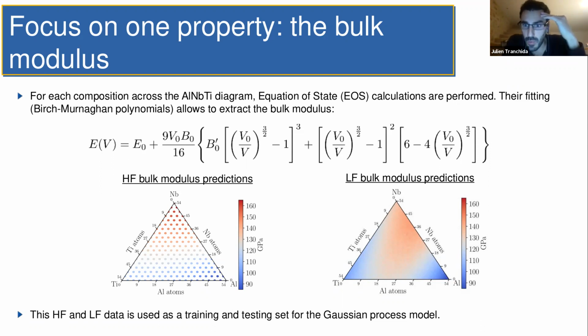Yes, that's more or less all I wanted to say. Oh no, yeah. As you can see, if you remember well, the training set was mainly composed of equicomposition data and data at the niobium, aluminum, and titanium configurations, for those compositions. And as you can see, those are the ones we are recovering quite well. Then when you get out of those compositions, of course, you're doing much more poorly on the calculation. On the low fidelity calculation, you have that kind of red cloud in the middle spreading around, and that's not really what you see on the high fidelity calculation.